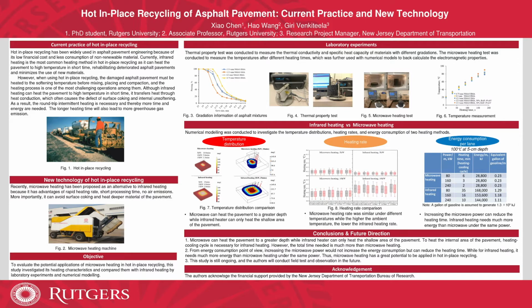So based on this, the thermal property test was conducted to measure the thermal conductivity and the specific heat capacity of the material with different gradations. We can see in figure 3 and 4. Totally, there are 4 different asphalt mixtures that were typically used as surface course in New Jersey, and they were investigated in this study. Different geometry specimens of them were made for the test. The microwave heating test was conducted to measure the temperature after different heating times, as shown in figure 5 and 6. The heating results were further used to back calculate the electromagnetic parameters of the material in the numerical model.